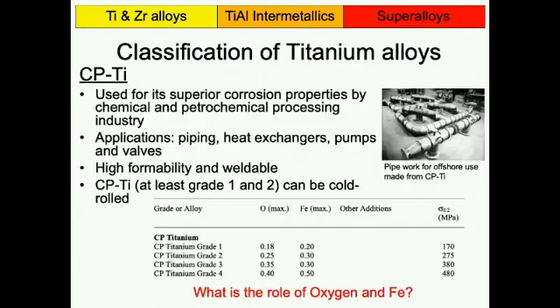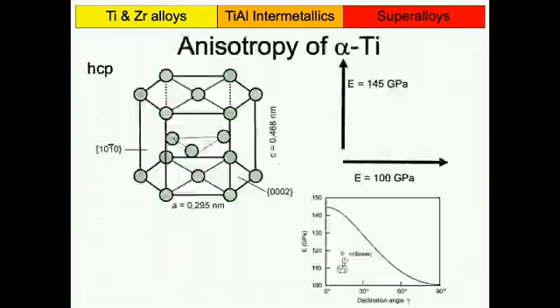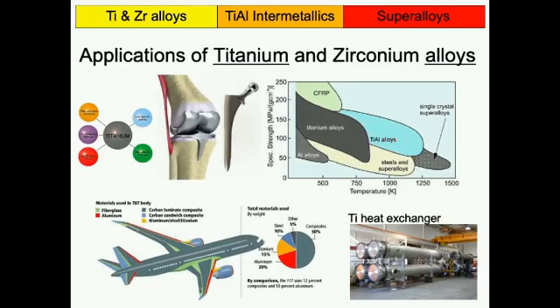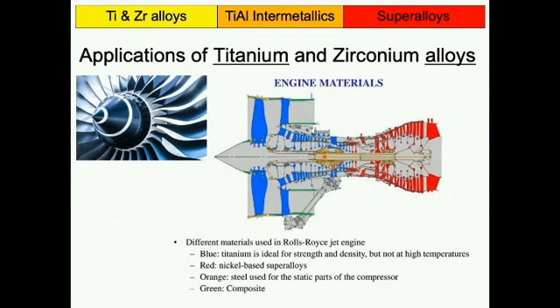So, I don't know if I can quickly go all the way to the beginning where I had this one slide here. You see, you have titanium at the front here, and then you cross over to nickel. And the temperature in that engine goes up, and up, and up, is highest somewhere here, and then falls down again near the outlet. So you need to swap over from titanium to nickel somewhere, because nickel will give you higher temperature capability than titanium. Now if you have a titanium alloy which has much better high temperature capability, you can push back the nickel a bit further and reduce the weight. That was the thought process when these alloys were developed.